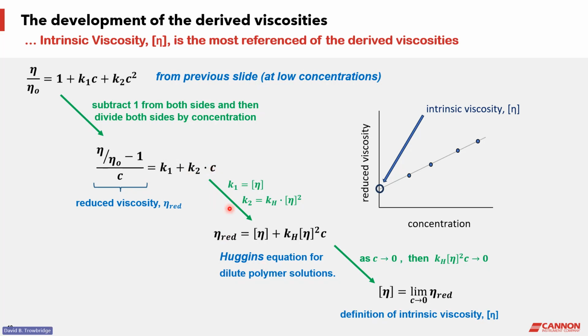Then Huggins looked at this, an early worker, and he realized that K1 is actually the intrinsic viscosity that Staudinger had been using, and K2 is equal to a new constant times the square of the intrinsic viscosity. So Huggins made the substitutions of these into his version of the working equation, and this became referred to as Huggins equation.